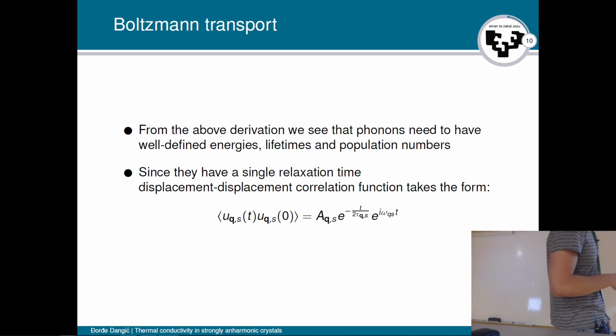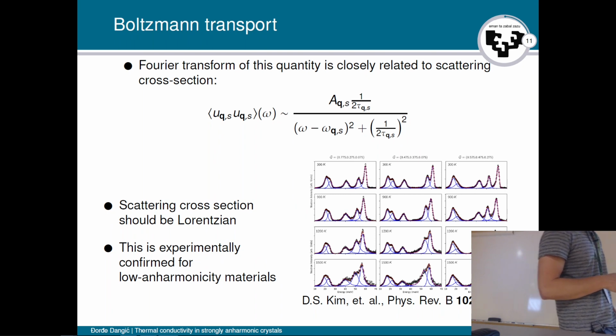If that was true, then the displacement correlation function that we discussed several days before would be some decaying oscillations. And then the Fourier transform of it would be Lorentzian, which we already, again, discussed. So this is nothing new for you guys. And obviously, the line width of that Lorentzian profile is related to the phonon lifetimes that we have. This Fourier transform, or the correlation function, has been shown in the past few days to be related to the scattering cross sections, either in Raman, neutron scattering or X-ray scattering, and it's also related to the signal in the infrared experiments.